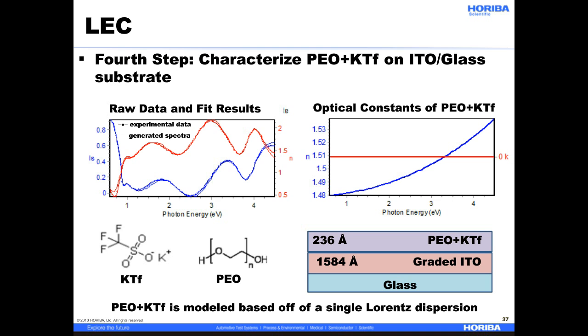On the right, the optical constants of the mixture material, PEO plus KTF. They're very simple because K is 0 over the range that we're looking at, and N is decreasing with wavelength, or increasing with increasing photon energy. So this tells me that PEO plus KTF is a transparent material, with no absorption over the range we're working with, so we can use a simple single Lorentz oscillator to model this material.